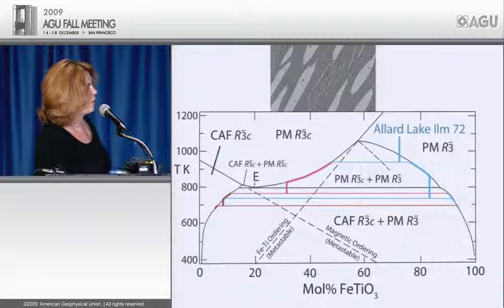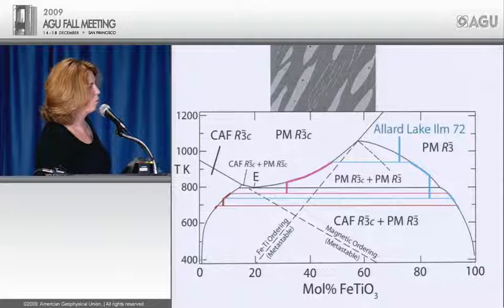It would have crystallized. It would start to exsolve quite early, and this is how we developed the large coarse exsolution. And then that exsolution would have then further exsolved and created finer exsolution, both in the ilmenite host as well as in the hematite host. And the final exsolution comes out.